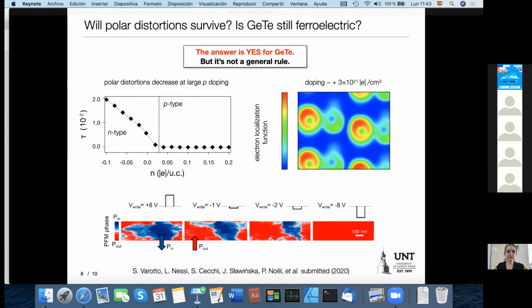Again, we took it into account explicitly, and we demonstrated that the polar distortion will decrease very slowly. So the hole concentration that would remove the distortion would need to be of the order of 10 to 21, which is about an order of magnitude more than we have for the experimental samples. The interesting thing is that if we have n-type doping, the polar distortion doesn't disappear at all. So probably this is also an interesting direction to study. So for germanium telluride, indeed, we can maintain this polar distortion. It is related to the detailed mechanism of ferroelectricity and the lone pairs, which are the fundamental mechanism behind the ferroelectricity.